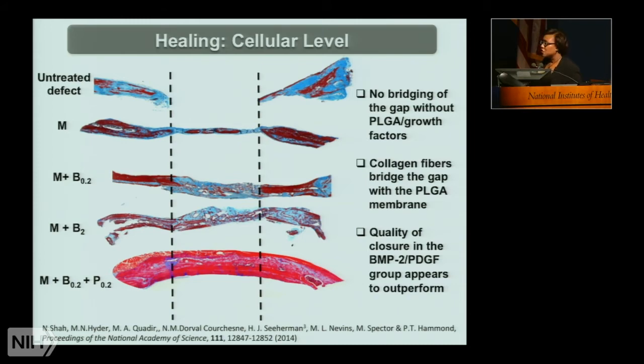And if we increase the dose by a factor of 10, we simply get a big lump of bone that has very little relationship with the margins. It's essentially a kind of cap of bone that's been formed. However, when we look at the cascade of growth factors, PDGF first, followed by BMP2, if you remember the time scales, PDGF is released more rapidly and over the first week, and BMP2 is being released over this period of a month.